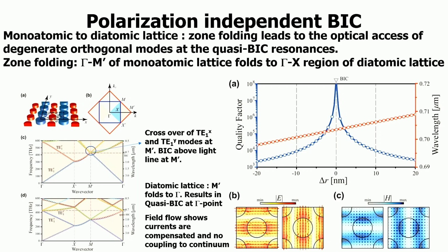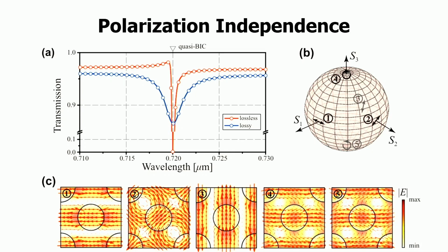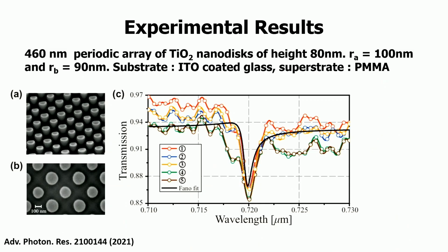So we combine two different lattices, blue and red are different size disks. So basically the zone folding leads to the M point folding onto the gamma point. So these two are orthogonally polarized modes. Because of which, we can get X and Y polarizations at this gamma point in a diatomic lattice. So this leads to polarization independent excitation of bound state in continuum resonances, which we experimentally demonstrated.